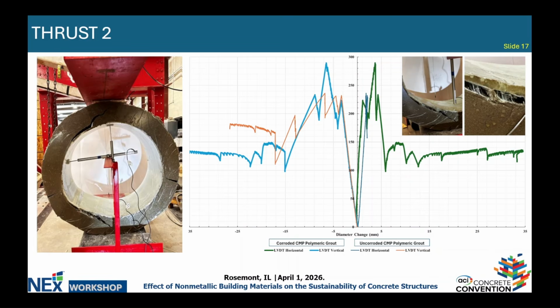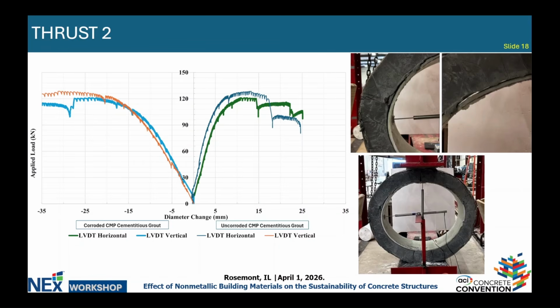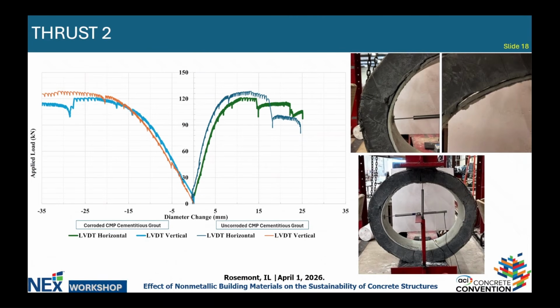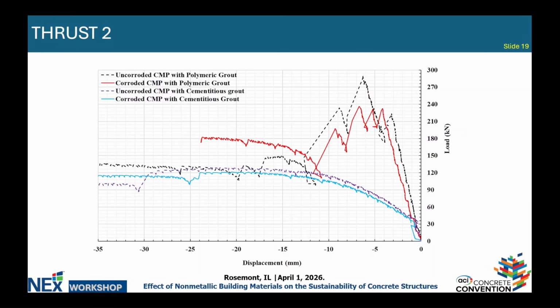The beauty about the polymer concrete is that it enabled a fiber bridging option. So you can actually see those fibers really being engaged in this testing until failure. In the cementitious concrete, on the other hand, you absolutely see a complete detachment of the grout from the GFRP slip liner itself. So you see these clear differences between these 2 grouts, where polymeric concrete is able to engage those glass fibers in the GFRP slip liner, whereas a cementitious grout is unable to get that efficient load transfer possible. So this is a very key observation from our study.